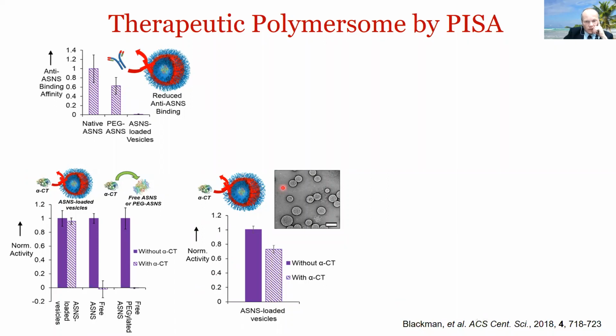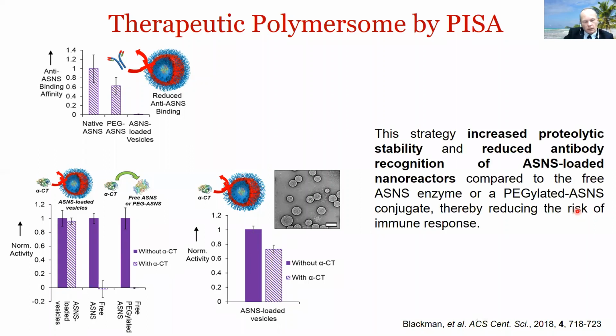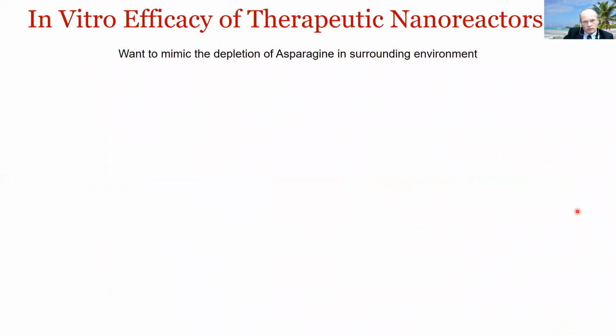And just shown here is a similar experiment, but now performed over 7 days. So we really have a very good long life and good stability using our encapsulated approach. So we've been able to increase the proteolytic stability and reduce the antibody recognition, which is great. And this in turn, we propose, would reduce the risk of an immune response. But we really wanted to see if we could, in vitro, demonstrate the efficacy of these therapeutic nanoreactors.